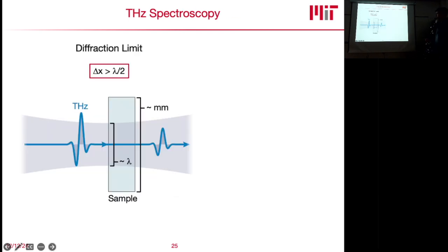So, just to give you a little refresher, this is typically how we do terahertz spectroscopy. In macroscopic samples, this is very easy. You take your terahertz light field and you focus it down. You cannot focus terahertz light smaller than its diffraction limit, and this is determined by its wavelength. The smallest terahertz spot that you can generate is half its wavelength, because otherwise your terahertz wavelength is ill-defined. For millimeter-sized samples, this is not a problem, because terahertz wavelength is usually on the order of 300 micrometers. So this fits very well.